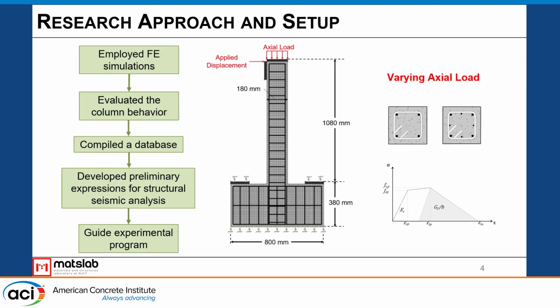So what we did was we employed finite element simulations. In the middle here, we have our cantilever column that we simulated. We applied a lateral displacement in a single direction and an axial load at the top. Using these finite element simulations really allows us to vary not only the axial load, but the reinforcement ratio and the material properties. And we can see how each design parameter is changing that column response.